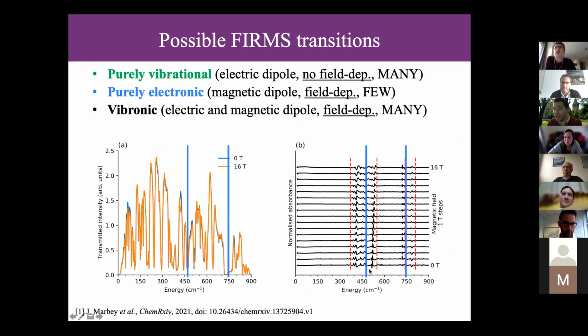They could be there, but of course, what we also know is that the infrared dipole absorption intensity of an acoustic mode is so much lower than that of a localized mode, right? Because if you're just shifting the whole molecule, you don't change really the dipole moment. So it's assuming the rigid molecule, but they're never rigid, so they are coupled. Of course, and in the pseudo-acoustic region where you have the different molecules in the primitive unit cell moving near each other, then again, they're non-zero.